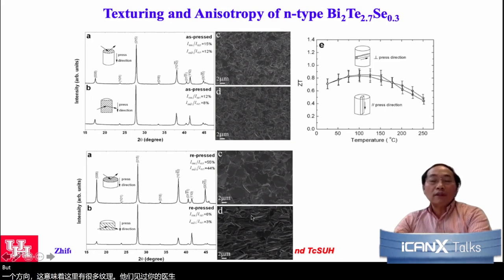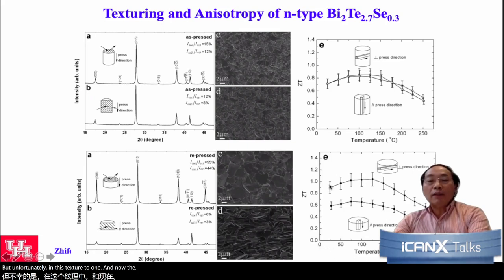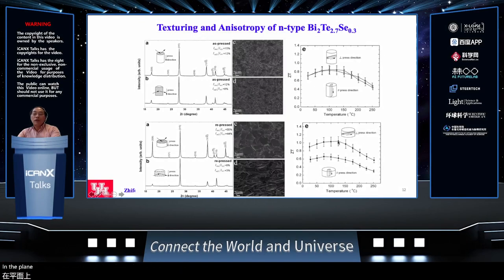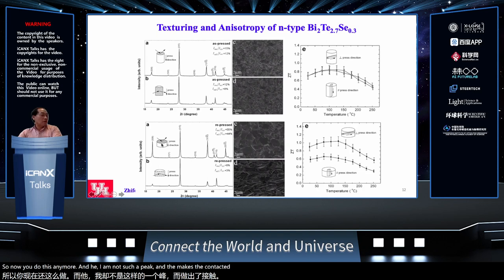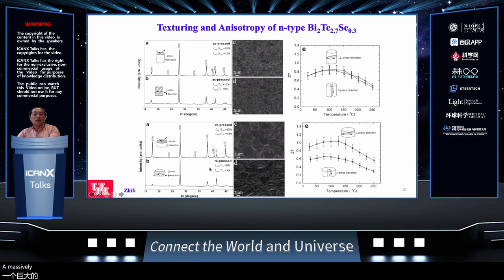But unfortunately, with this textured one, the property indeed, in the plane, you do have higher ZT, but out of the plane, much lower ZT. Due to this anisotropy, it makes the contact fabrication much more difficult, which is why we're not able to commercialize this improved bismuth telluride, both N and P, at massive scale, because the good direction is the other direction, for which we cannot make contact.